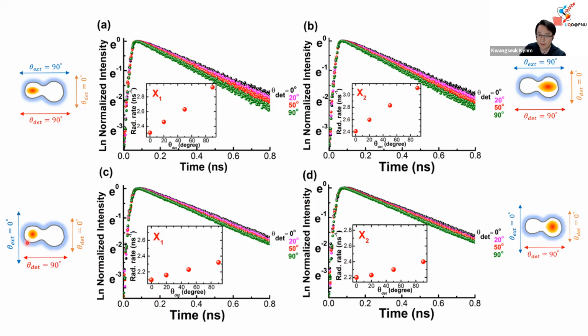With a 0 excitation, on the other hand, it shows a linear dependence, but if you compare with the case of a 90-degree, the magnitude is different. It's 2.3. Here is very large because the oscillator strength along the 90-degree here is very large compared to that size. Again, the same feature.